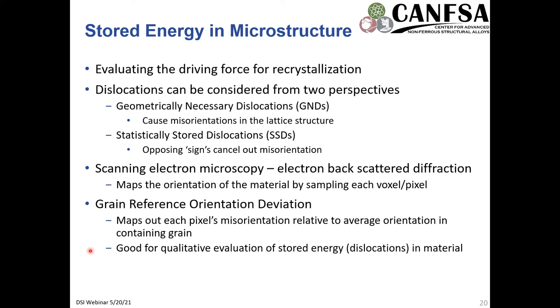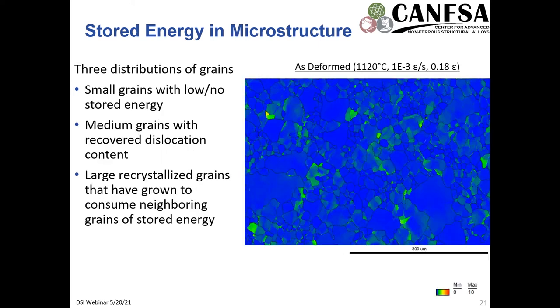And this is good for a qualitative, not a quantitative, evaluation of stored energy or dislocations in material. I'm not really mentioning that grain boundaries are a source of stored energy, that they're non-equilibrium, so that in and of itself is a driving force, but we're mostly focused here on dislocation density in the context of isothermal forging. And so within the microstructure in the as-deformed state, if we took this material and did a supersolvus heat treatment in the right conditions, or wrong depending upon your perspective, this would create abnormal grain growth, as we demonstrated in many different specimens.